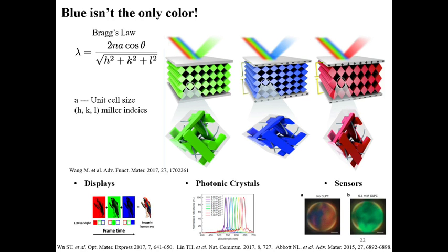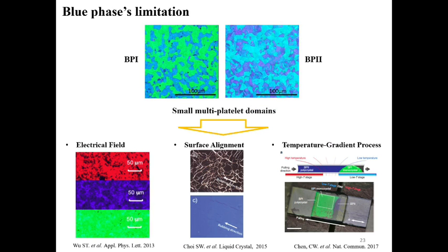which indicates that they have added some biomaterial into the system, so you can detect whether there is an additional composite in the system. However, in order to use this kind of blue phase liquid crystal material, they have some limitations. First, I forgot to mention, they have two different phases. Blue phase 1, which often forms a body-centered cubic structure. Blue phase 2, which often forms a simple cubic structure.